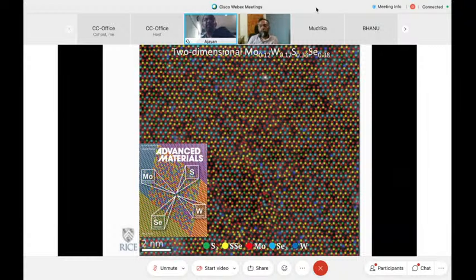Finally, again without going into details, I want to say that we were able to create some beautiful alloys of 2D sheets. This is an example where you have four components, molybdenum, tungsten, sulfur, selenium, and it's a complete elemental map and energy filtered image from a STEM microscope showing the positions of all the atoms. You can distinguish between sulfur and selenium columns, and even sulfur on selenium or selenium on sulfur. Again, a lot of image simulations go into this. But the bottom line is that we are now able to create nice alloy sheets of these 2D structures, and we are looking at various properties that these have.